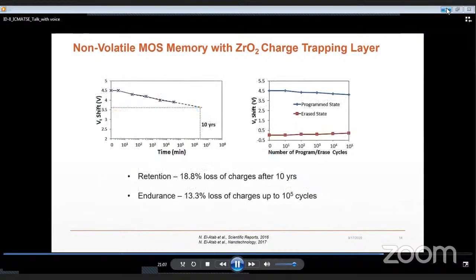The endurance characteristic of the memory is also analyzed by conducting program erase cycles up to 10 to the 5 cycles. The measured results indicate around 13.3% of the initial stored charges are lost after 10 to the 5 cycles.